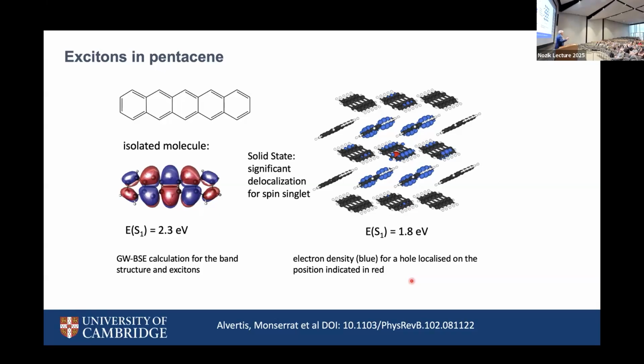electrons and holes are very strongly bound in molecular semiconductors. Just the electrostatic attraction between an electron and hole is stronger in any of our organics than it is in silicon or gallium arsenide, because the background dielectric constant is much smaller. So if you absorb a photon in some silicon at room temperature, we expect to have a free electron and a free hole. They will diffuse away, and you could collect them on a solar cell.